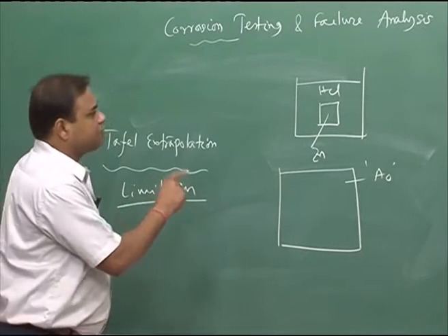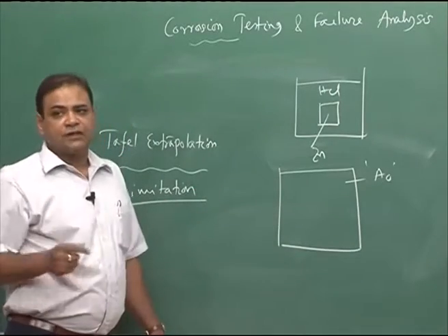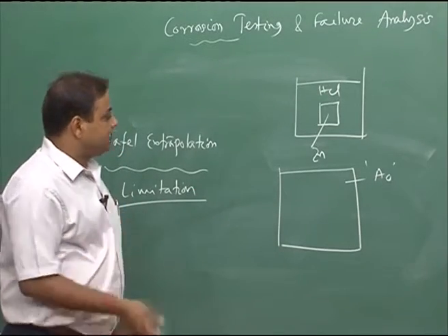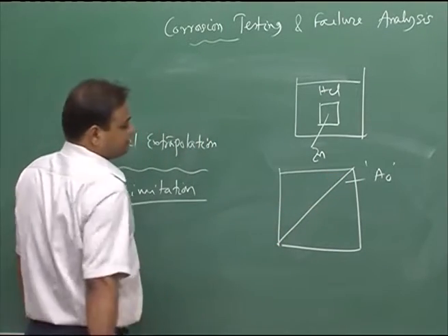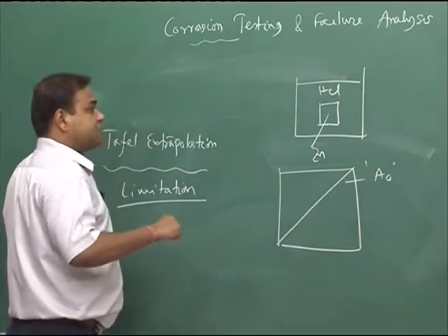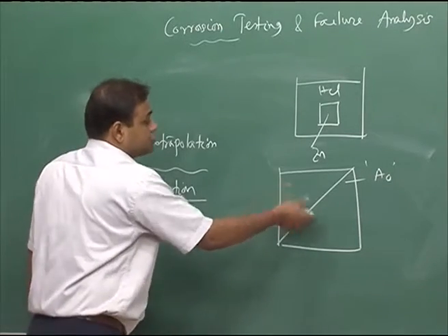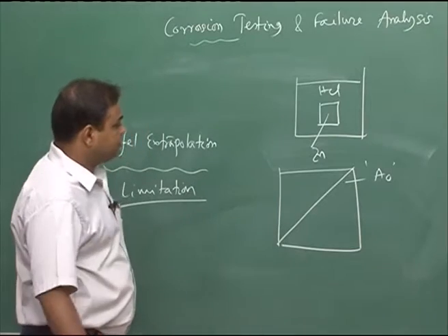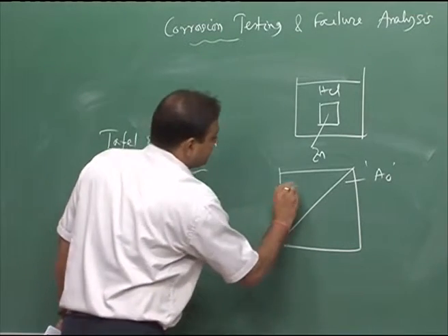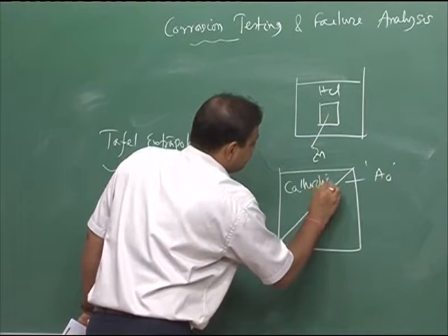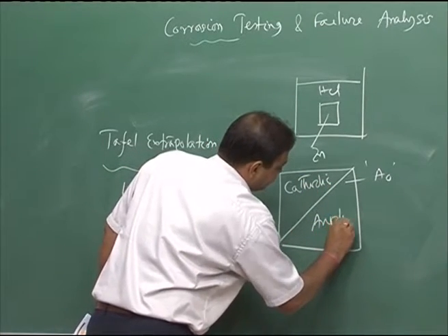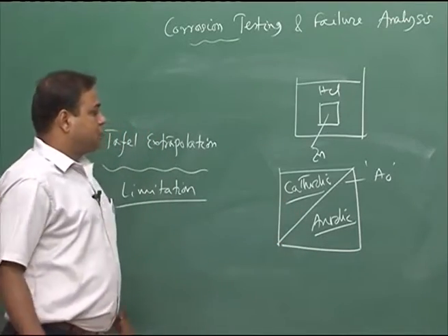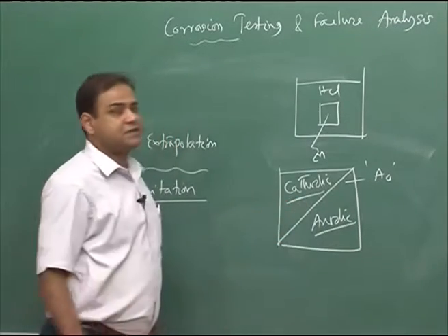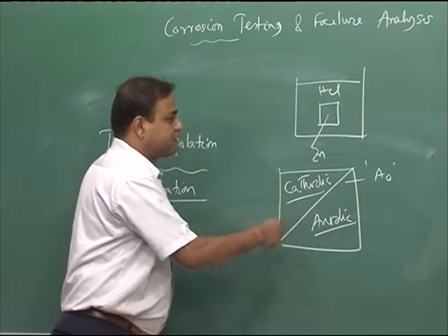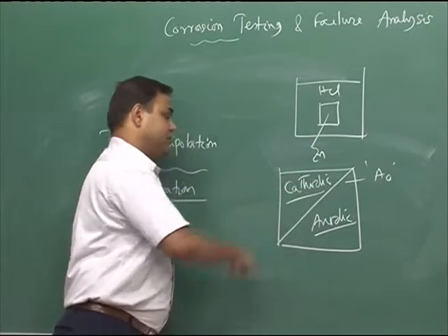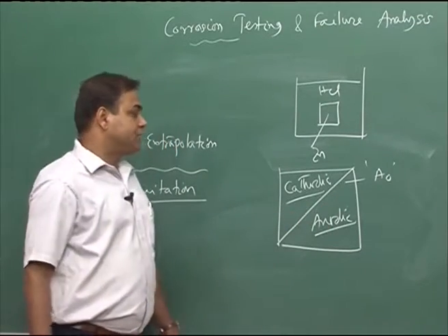But actually some part of this area would be cathodic side, some part would be anodic side. If we consider statistical uniform distribution of those two reactions, let us say only half of this part is, so if we consider this is my cathodic side and this is my anodic side, then only half part is getting dissolved, because the cathodic part will be protected due to the cathodic reaction happening on that part, but only the anodic side will get corroded.